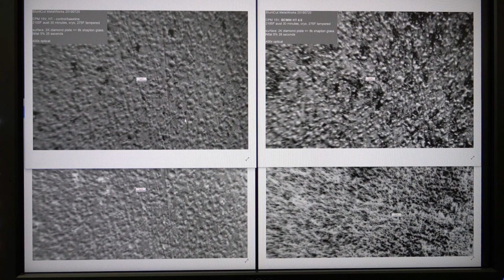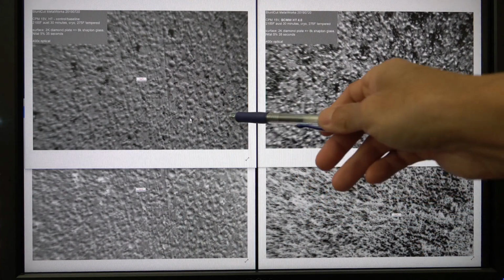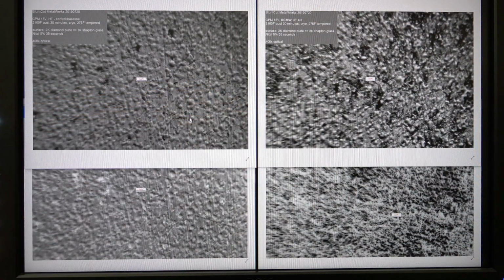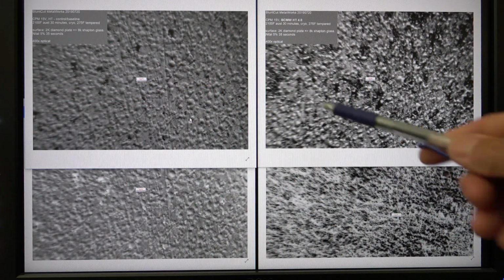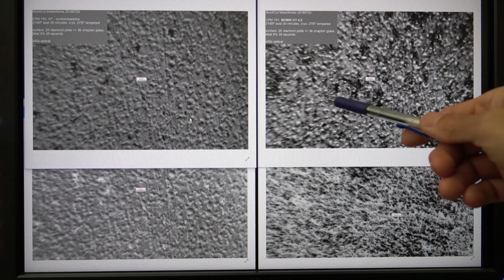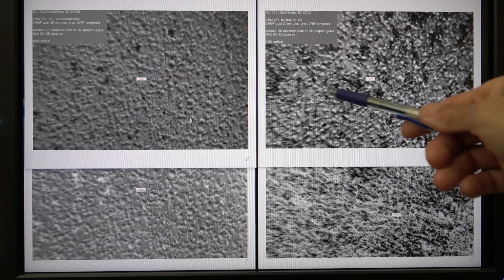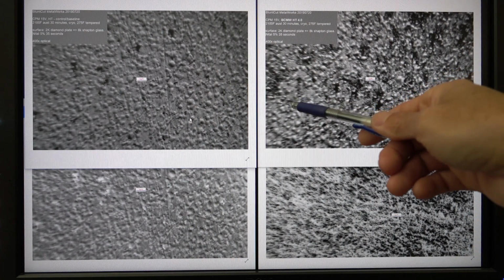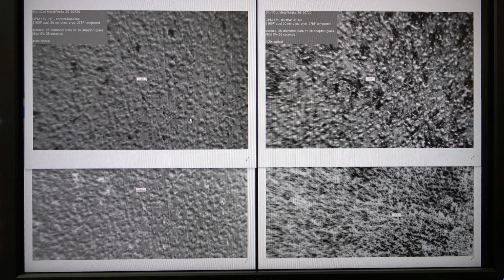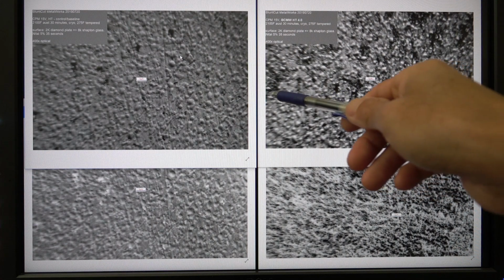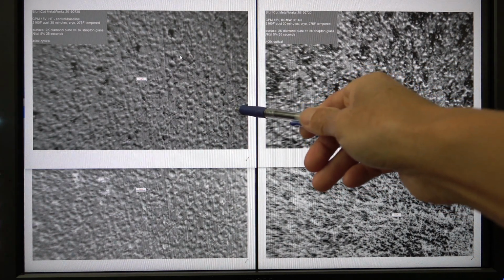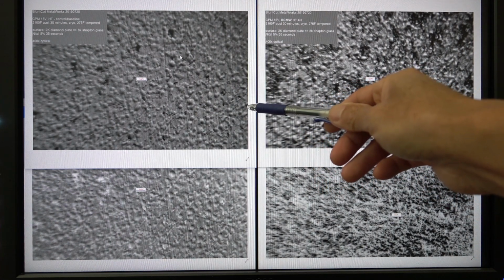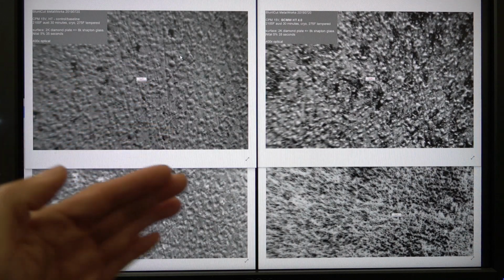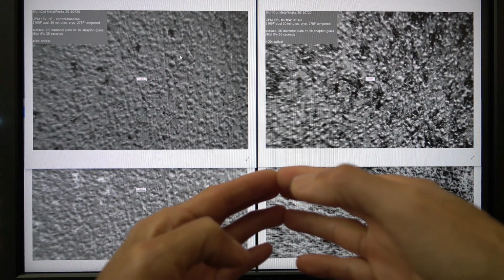So this shows the flat surface, but if you now draw a line across here and call that your apex, your edge, first of all, the more protrusion of carbide, the higher. The edge will contain higher protrusion of carbide here, because again they have the strength, they have the support in order to hang on or to withstand the external abrasive. So when you have a knife, the more matrix you have, when you run into abrasive, the more burdensome, the more rounded the edge will become. And that's why it will feel dull.